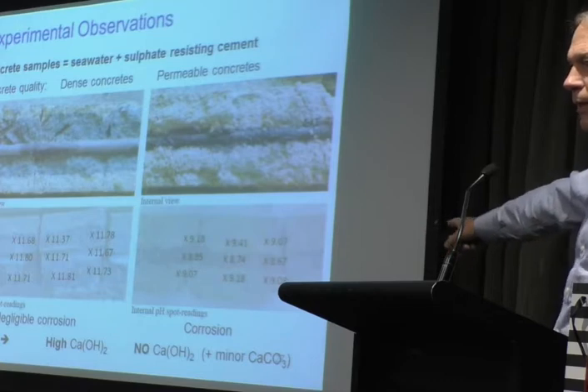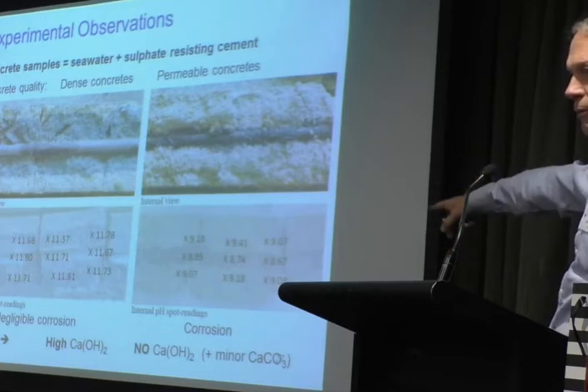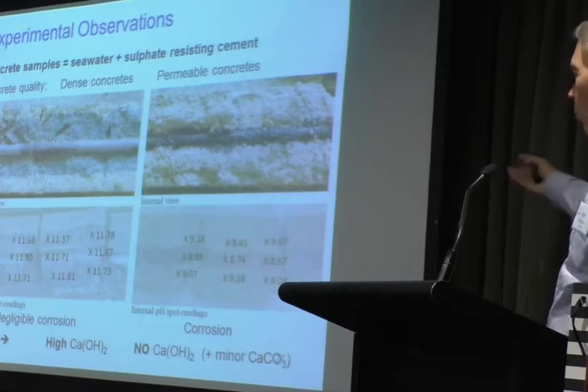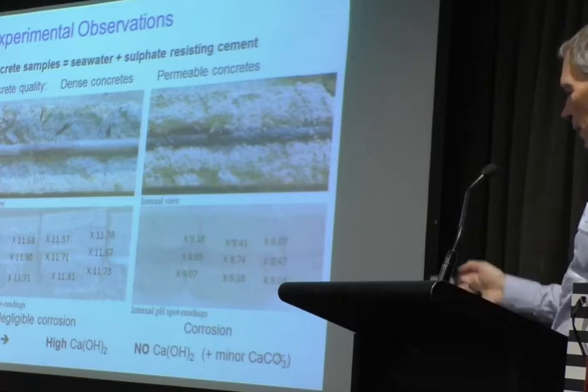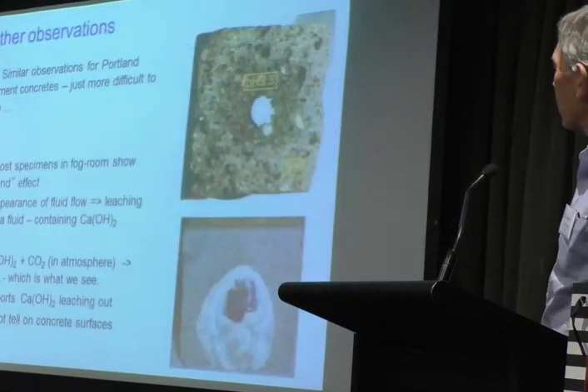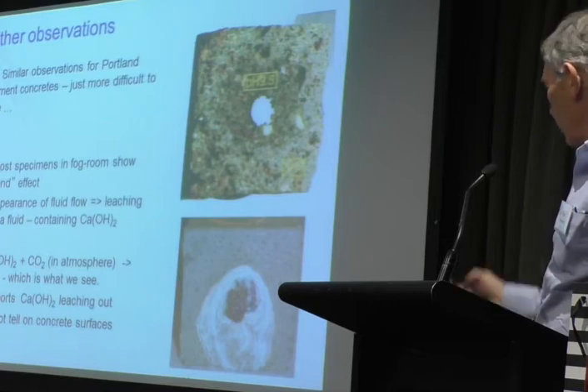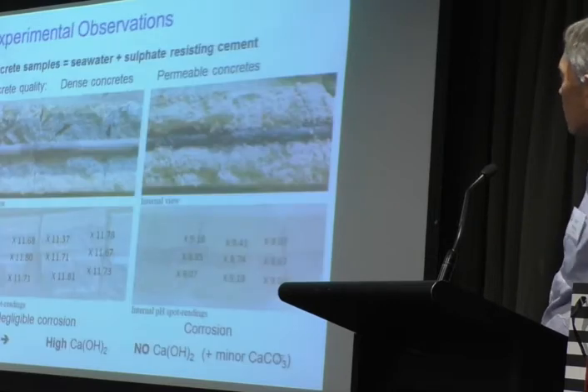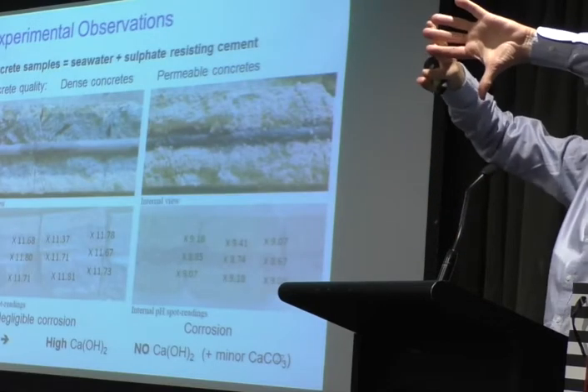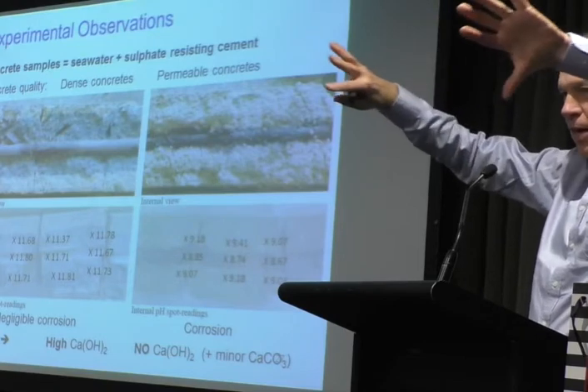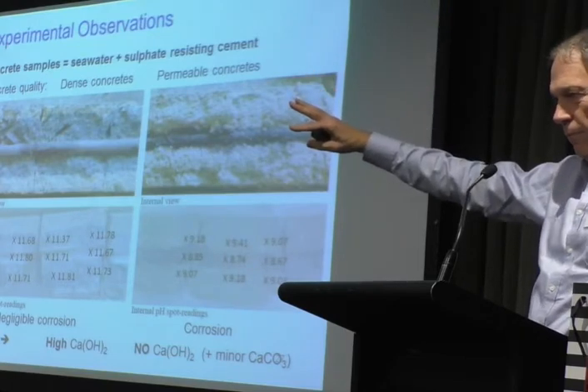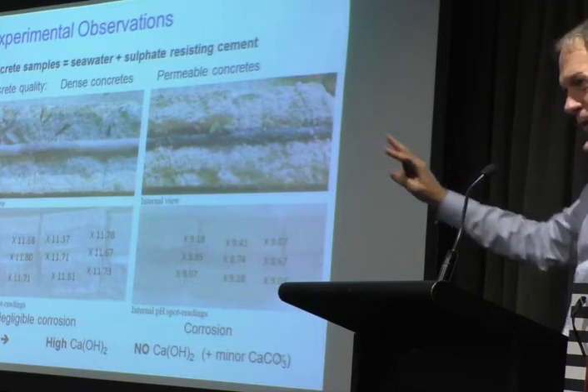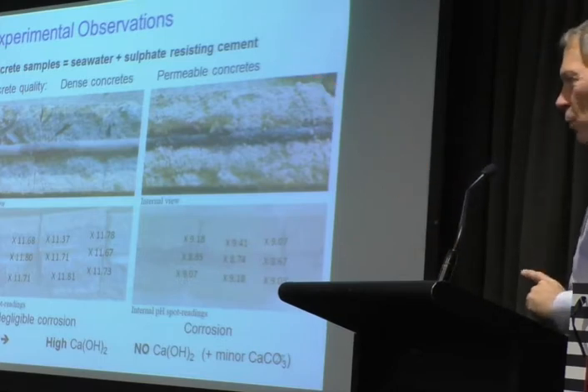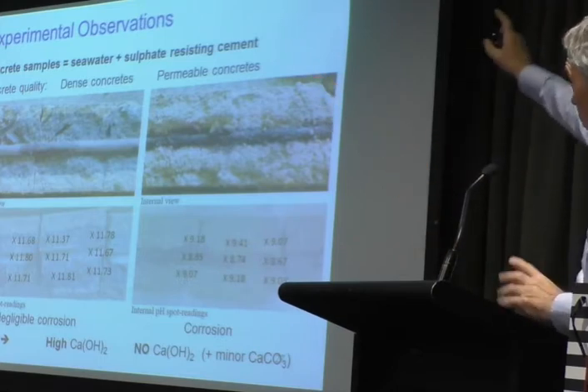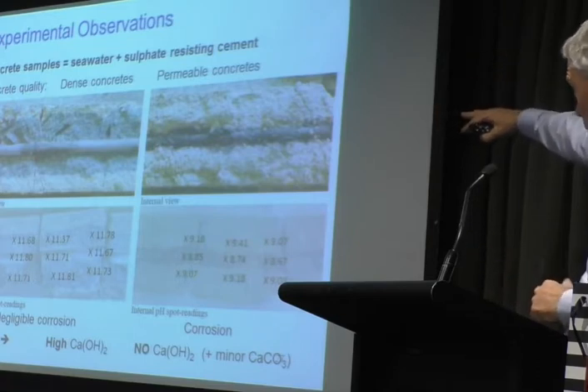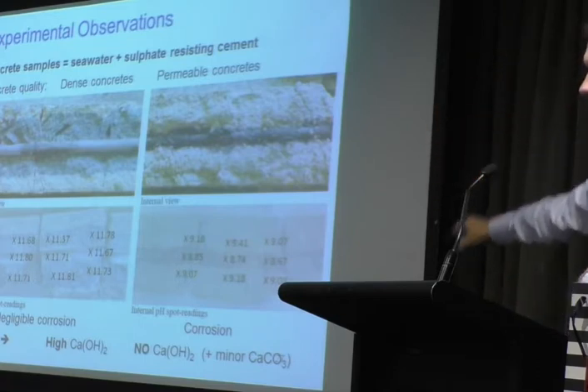So there was no alkalinity anymore to keep the bars passive. So then you say, well, how did that come about? And then you think, the only mechanism that's possible, let me go back. The only mechanism that's possible is that the alkalis leach out. And then you ask yourself, is that really the mechanism that's causing it? Because ultimately, when all the alkalis have leached out, then you've lost your alkalinity and the bar can corrode.